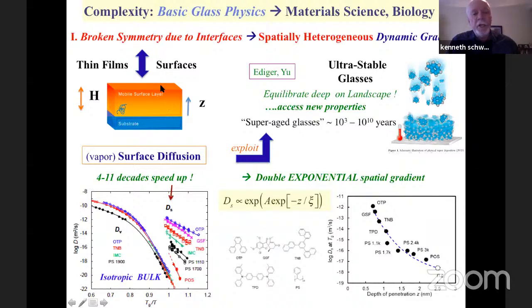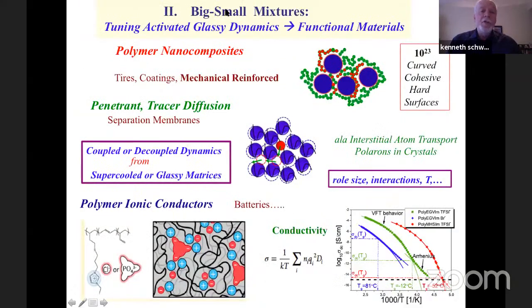And it's this extra mobility at the surface that underlies his beautiful work in the area of ultra-stable glasses, where he can access low energy points on the landscape, effectively equivalent to super aging. My own interest is also many hybrid systems where you mix small and large particles. I'll just mention them. Polymer nanocomposites, where when you put in particles, you can tremendously change the polymer subsystem.